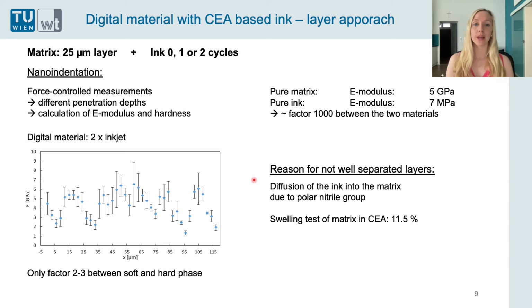And we also did swelling tests where we put a molded matrix plate into the cyanoethyl acrylate and measured the mass increase after 22 hours at 50 degrees C. And here the mass increase was 11.5%, and this is quite high. So we think this is the reason for the not well separated layers, but nevertheless we did further tests.